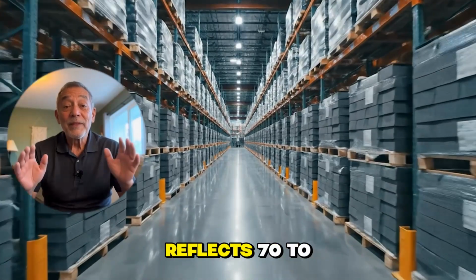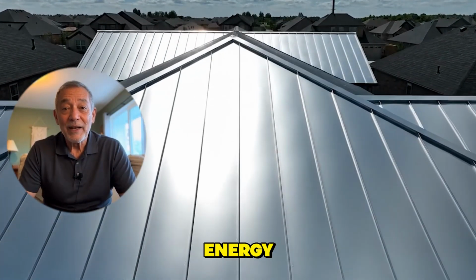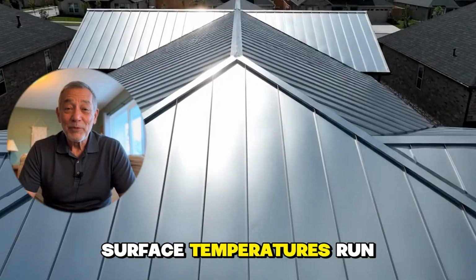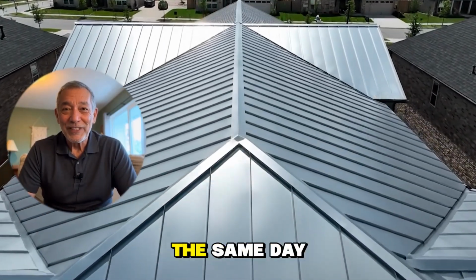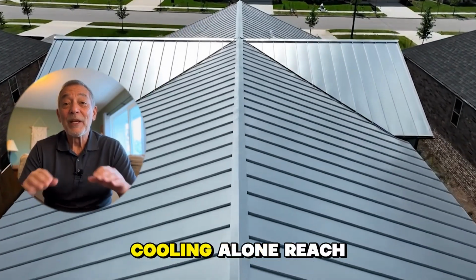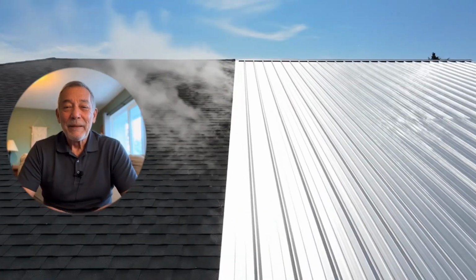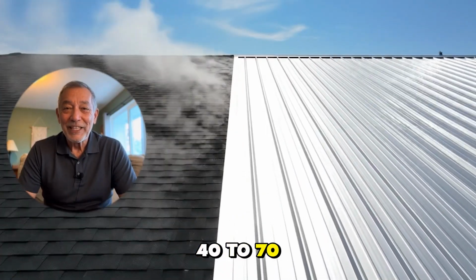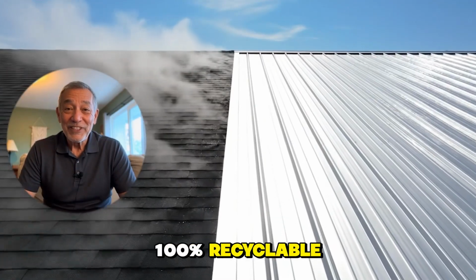A metal roof reflects 70 to 80% of solar energy instead of absorbing it. Surface temperatures run up to 100 degrees cooler on the same day. Energy savings on cooling alone reach 50%. The material lasts 40 to 70 years and is 100% recyclable.